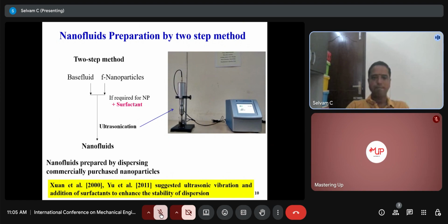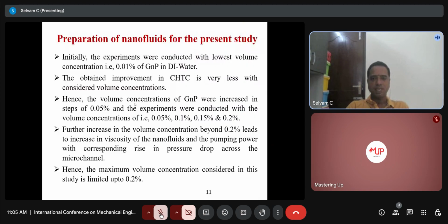And initially, we selected deionized water as the base fluid and graphene nanoplatelets as the nanomaterial. And initially we selected the volume concentration up to 0.01 volume percentage.